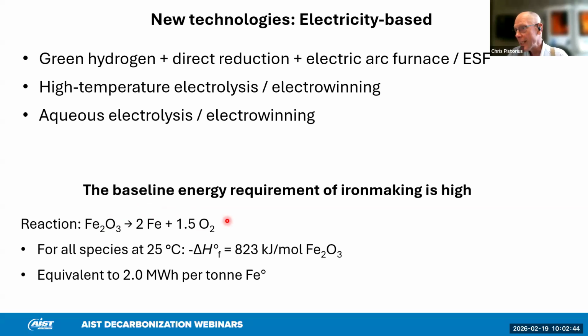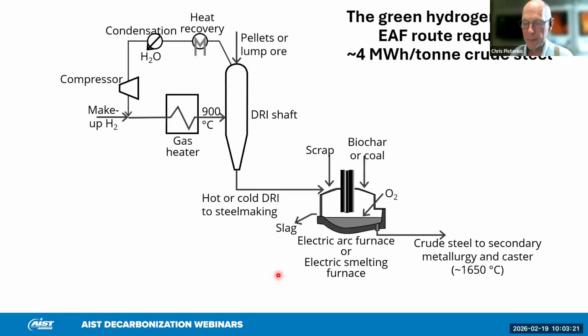So we need to provide at least that energy, and that turns out to be around 2 megawatt hours per ton of iron. So 2,000 kilowatt hours per ton of iron, about 5 times what we use in an electric arc furnace. And as we shall see, when we add in the other things we need around the plant, the typical number ends up around twice this, 4,000 kilowatt hours per ton of metallic iron, or roughly per ton of crude steel. So it will require a large amount of electricity, as Sarah pointed out.